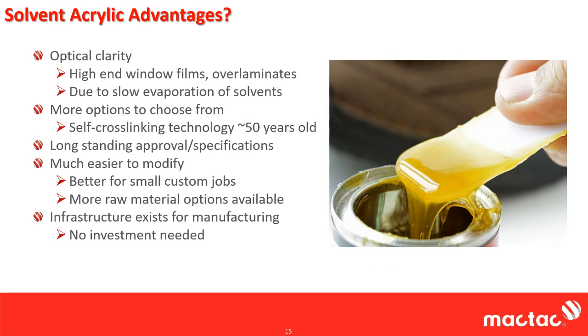We have not, and a lot of work's been done out there in the industry to try and make 100% solids be as optically clear as solvent-based adhesives. It just hasn't happened. So again, you can get a good clear coating out of a UV or a hot melt rubber. You can even get a good clear coating out of an emulsion acrylic, but you're never going to get that high-end optical clarity that you will out of a solvent adhesive.